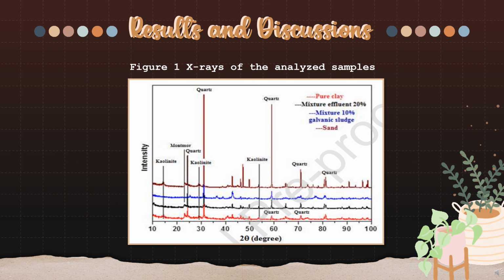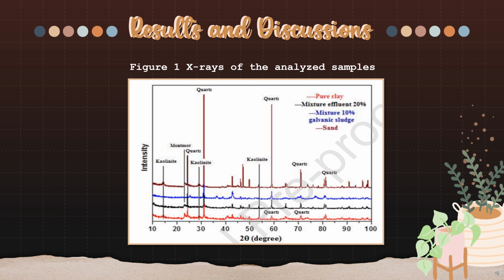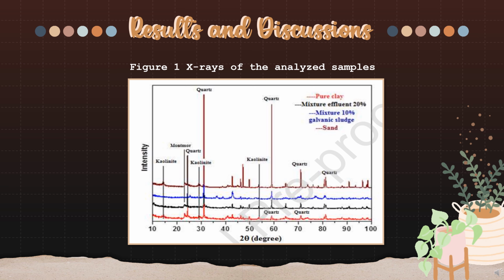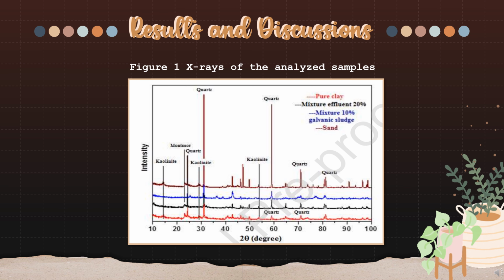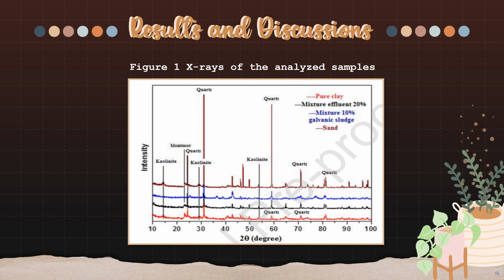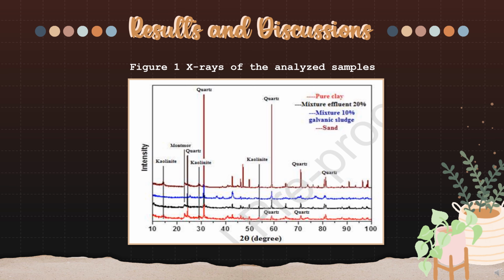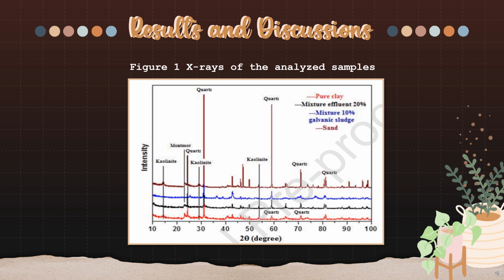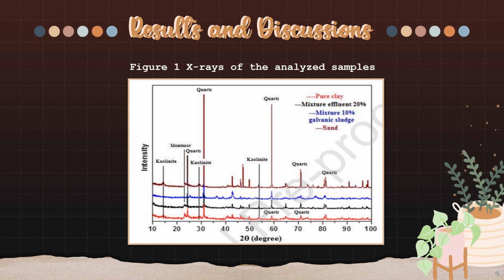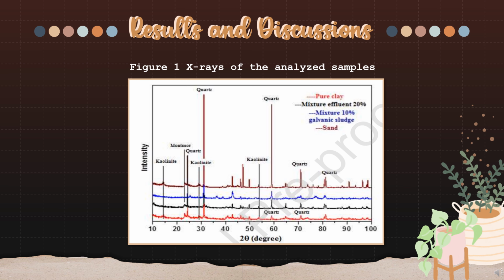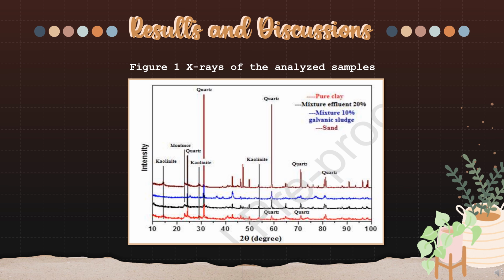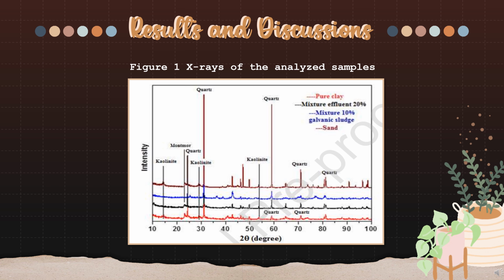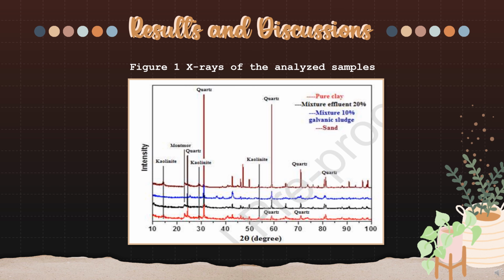The X-ray diffractograms for each clay are seen in Figure 1 and are compared to the diffractograms obtained for clays treated with galvanic sludge and effluent mixtures. Quartz is the most abundant material. Certain trends can be checked by the existence of clay minerals belonging to the kaolinite and montmorillonite groups. Only the general treatment was necessary in this case to acquire the mineral clays.